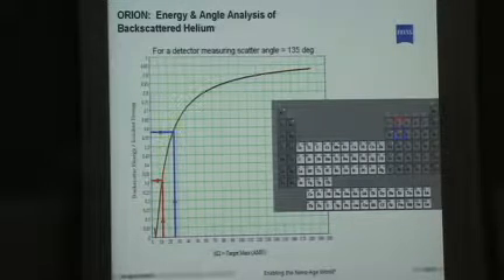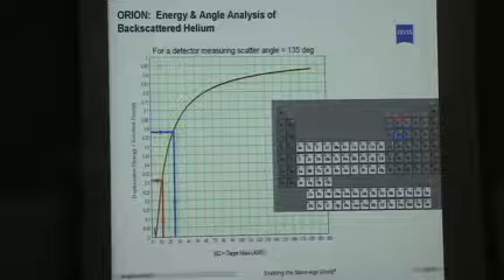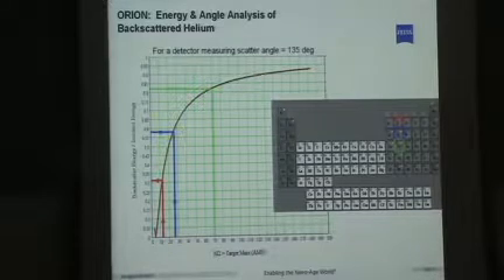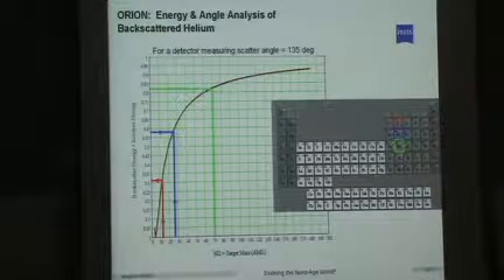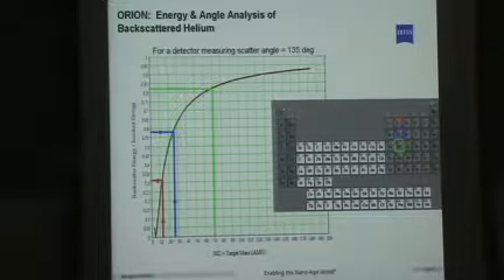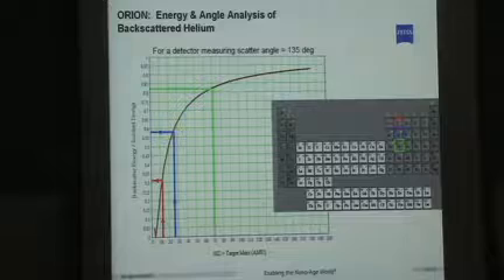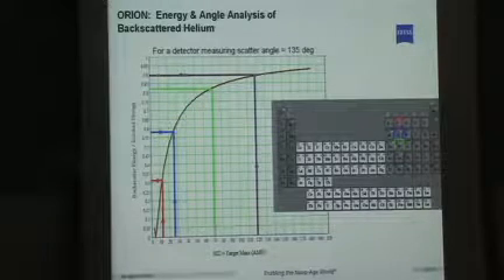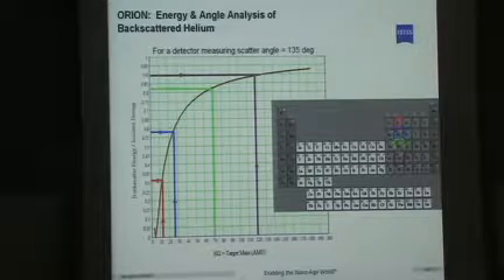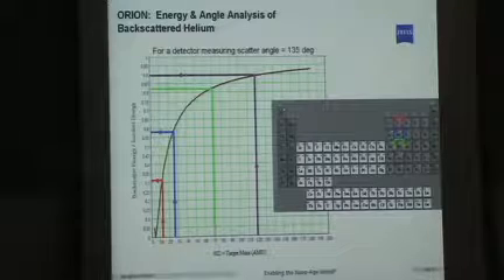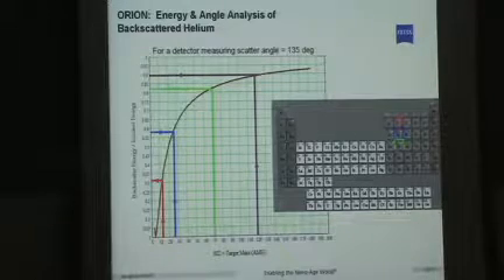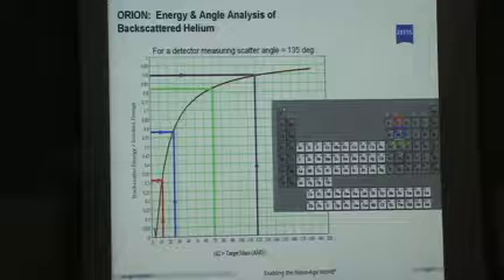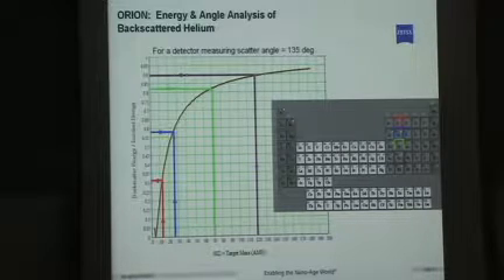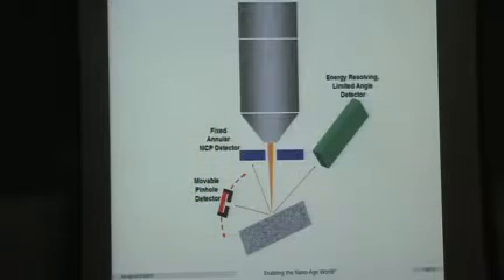If you wanted to identify silicon, the helium will bounce off with around 57% of its original energy. So this is a fairly simple way of deducing the mass of what you're imaging in a quantitative way. Now, it's a complicated scattering problem because you can scatter both at the surface or below the surface, so the interpretation of the spectrum is not trivial. But nonetheless, for thin film samples in particular, it's a neat way of doing metrology of that thin film. You can either identify what the composition is, or you can figure out how thick that sample is.